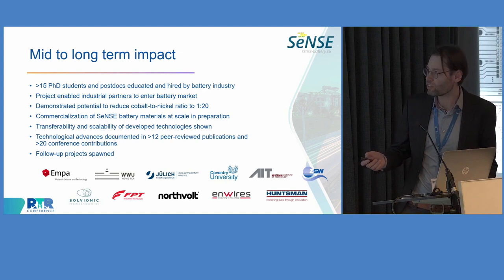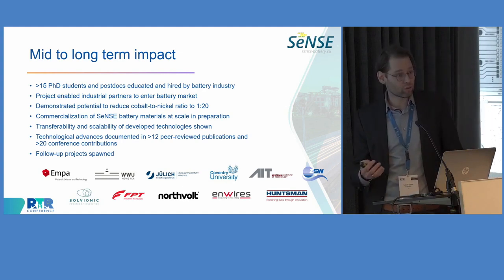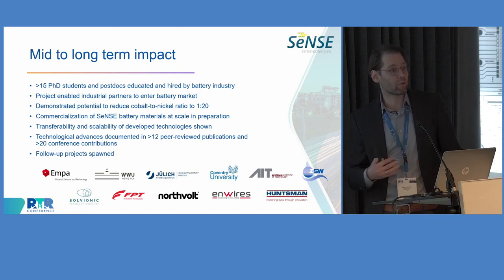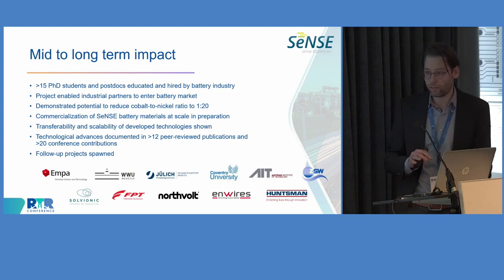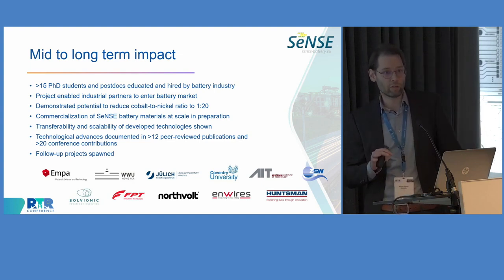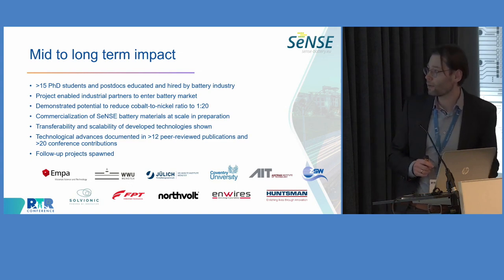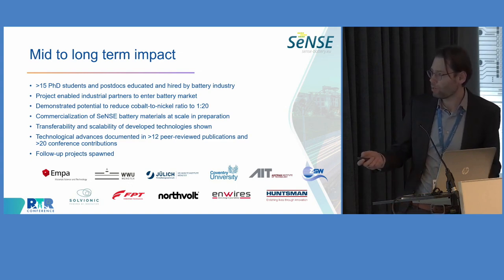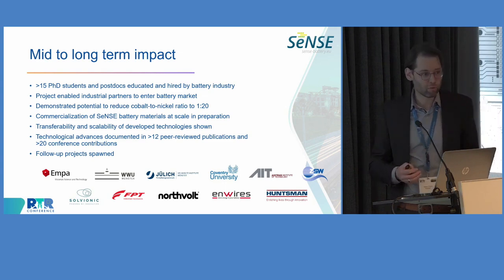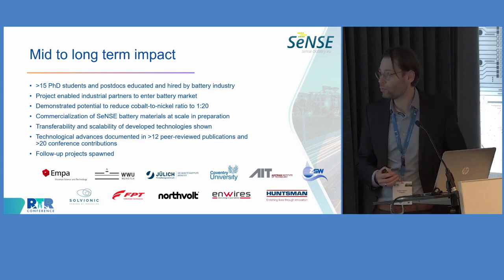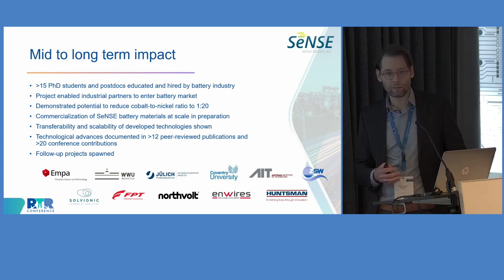A highlight for us, my first highlight, was to show that it's possible to reduce the cobalt content significantly in these nickel-rich NMC materials while maintaining good cycling stability. This goes into the environmental factor and into Europe's dependence on critical raw materials. I already mentioned that we have this follow-up project, and I think further follow-up projects are in the pipeline. We also have partners that are really close to commercializing technology that we've been developing in the project at a relevant scale. So that's also really nice.